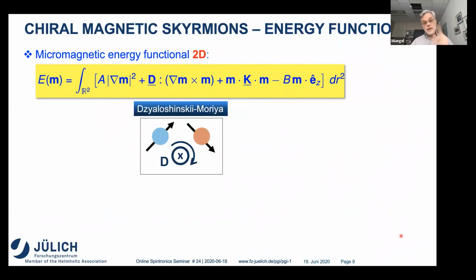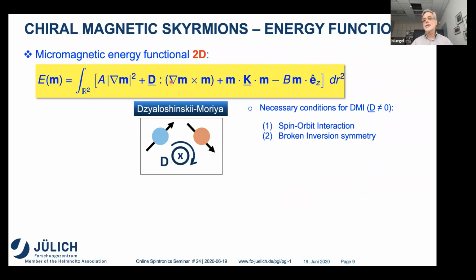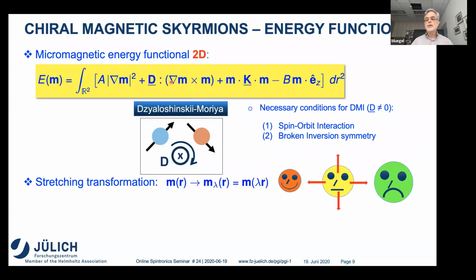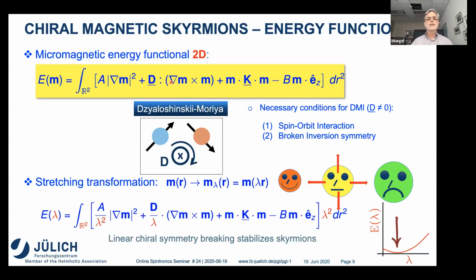So a crucial thing in this field of skyrmions is this Dzyaloshinskii-Moriya interaction shown here. This Dzyaloshinskii-Moriya interaction is basically a necessary condition for the skyrmions, and a necessary condition for the Dzyaloshinskii-Moriya interaction is the existence of spin-orbit interaction and a broken inversion symmetry. And if you do now our stretching operation, you see that due to this additional term here, which has the one derivative here, our stretching scales like 1 over lambda, and you finally have a minimum at finite lambda. So this Dzyaloshinskii-Moriya interaction stabilizes your skyrmion.